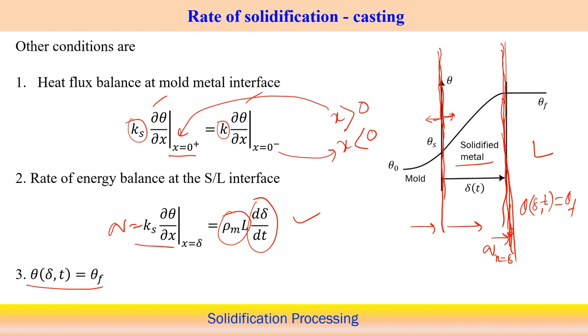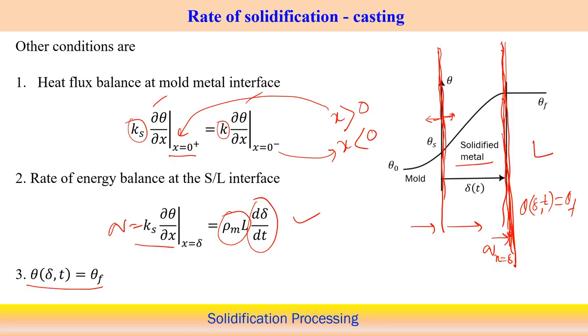of the liquid metal. At this point there is a continuous change of phase from liquid phase to solid phase, of the same material, the cast material. But in this case, one side is the mold material and the other is the cast material, the solidified metal. So here we can see two boundary conditions, such that we are maintaining the heat flux balance at the interface, and the same thing we can deal with at the solid-liquid interface. Here also we are maintaining the energy balance on both sides.